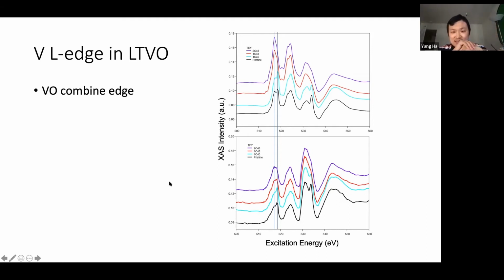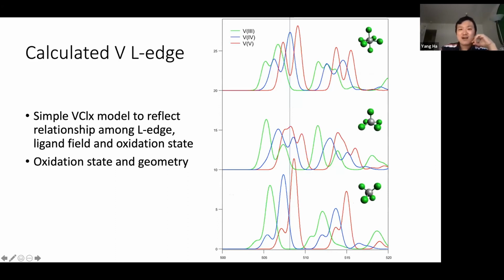So I then did a quick DFT calculation. It's really a cheap one. I just did the vanadium and tested different ligand fields with different chlorides. And I tested vanadium 3, vanadium 4, and vanadium 5 with different coordination environments.